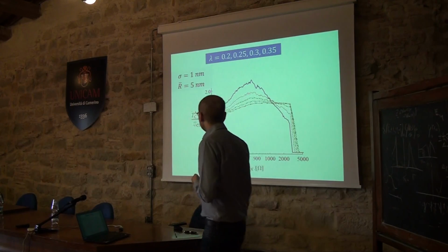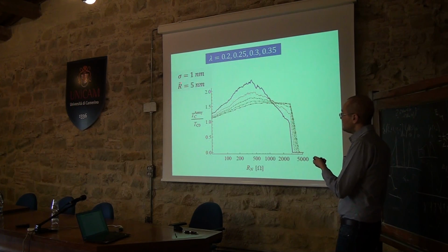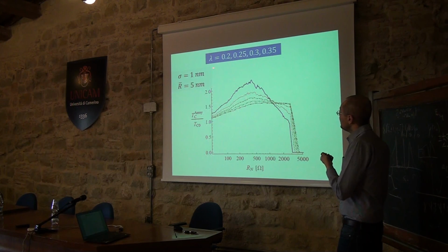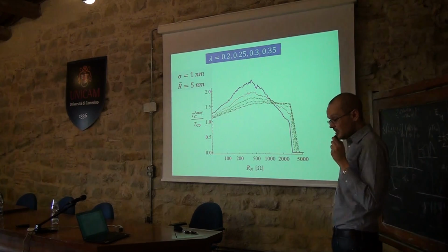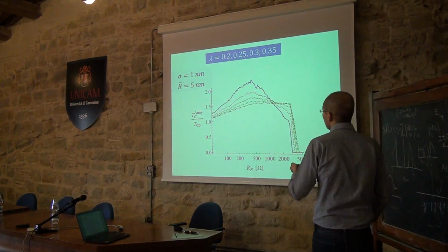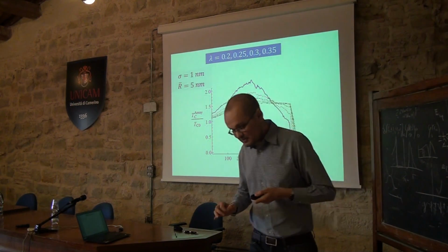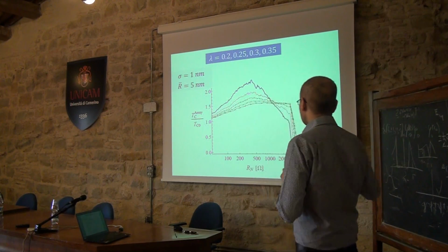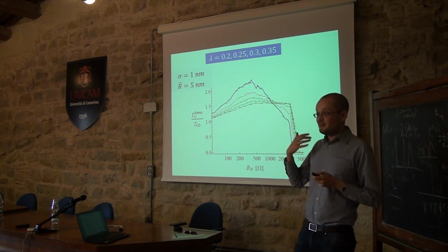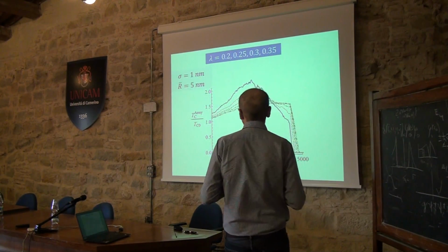Then let's say that we change the coupling constant, keeping typical values for the size and the standard deviation. Then we see something which is what we expect. If we work with a very weak coupling constant, the enhancement is bigger. Why? Because small changes in the density of states induce big changes in the gap in BCS. So that means that you get better results the more boring your material is, if you want to see it like that. Okay?